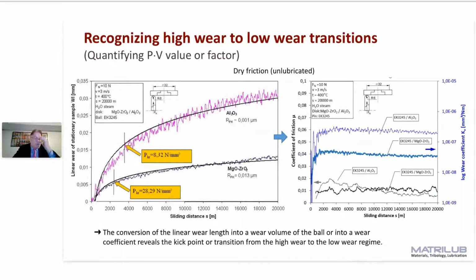But how can you now identify such a transition, such a critical contact stress? And you see here an example. It's a pin on disc test at 400 centigrade, 20 kilometers in hot steam. You have a point contact, and on the y-axis you see the total linear wear, which has a certain curve. But the wear volume does not go linearly, but it goes with the fourth power of the wear scar diameter, or the wear height, divided by the diameter of the ball.